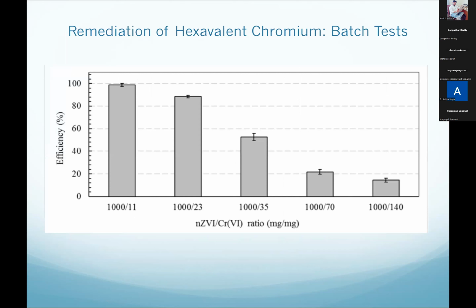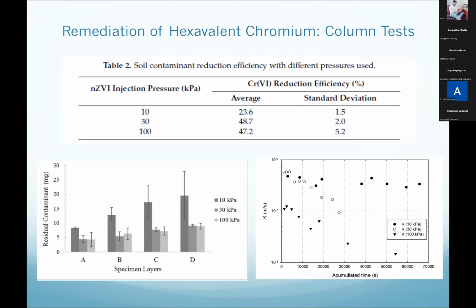And they tested with hexavalent chromium. This technology can be applied to chlorinated compounds and also hexavalent chromium or arsenic, where you can change the valence state. So basically, you're converting chromium 6 into chromium 3. So this shows the efficiency of this. And then we did different pressures and looked at how the permeability changes and how overall chromium reduction happens.